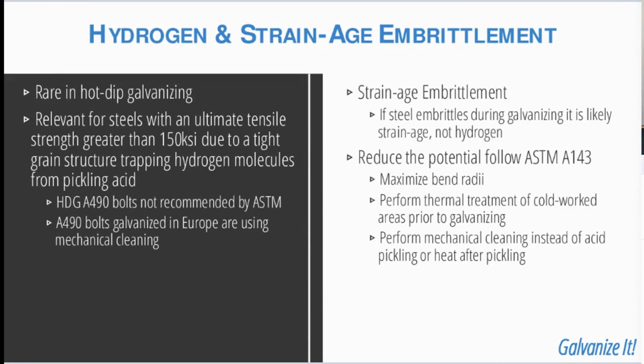Strain aging is a process where the steel becomes brittle in areas of high internal stress when they are exposed to elevated temperatures, such as those involved in hot dip galvanizing. Therefore, to reduce the potential for strain age embrittlement, all methods listed in ASTM A143 focus on reducing the internal stresses prior to galvanizing. All the recommendations are focused around that effort. For example, when you're bending steel, you want to avoid things like tight bend radiuses, and the bend diameter should be at least 3 times the section thickness, but maximized where possible if bending before galvanizing. Another area to address is holes.